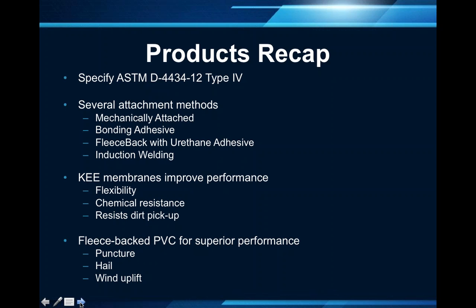As far as KEE, ketone ethylene ester, that is a plasticizer additive, a high molecular weight plasticizer that provides greater flexibility in cold temperatures and warm temperatures, and the most chemical resistance in terms of petrochemicals and animal fats and vegetable oils. And then lastly, it does the best job of resisting dirt accumulation on a clean white roof. As far as fleece back PVC membranes, that fleece back is a polyester fleece on the bottom side of the membrane, and it provides enhanced puncture, hail, and wind uplift.